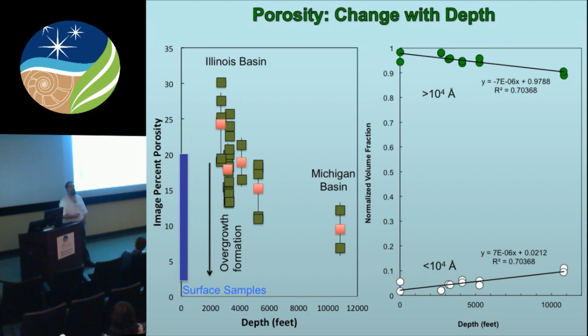However, if we add in the data from the small angle scattering so that we can look at what porosity is doing at finer scales, we can see essentially what I showed you in that scattering pattern before. While the larger size pores are becoming a smaller percentage of the total porosity, the finer ones are growing. Now, in part, this may be because you are compacting large pores into small ones, right? As you compact the sample, you're going to be reducing that size.